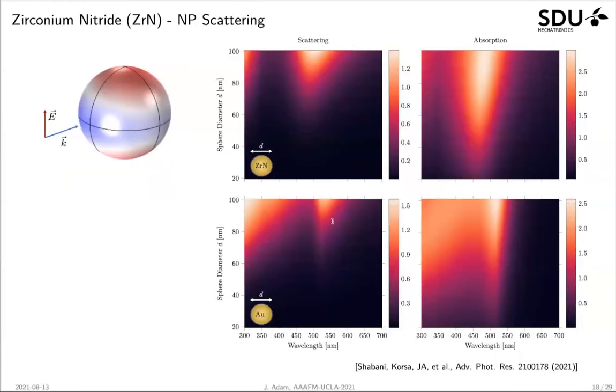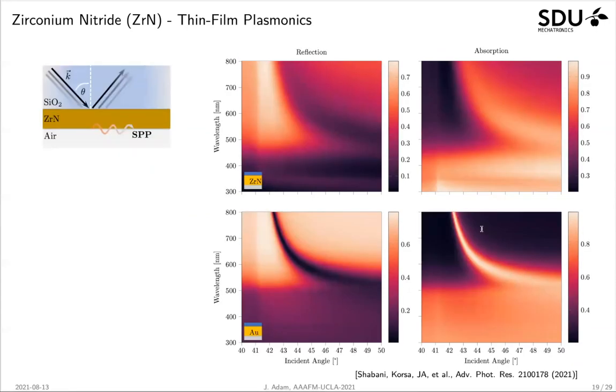Another question is whether this works in classical nanoparticle scattering scenarios, where the gold standard is literally gold. We compared ZrN nanospheres to gold nanospheres and found that in principle the resonances in scattering and absorption from the zirconium nitride sphere are a little bit wider than those from gold, but they show very similar behavior. In a classical Kretschmann configuration, the resonances created by gold are sharper, but zirconium nitride shows the same behavior with shallower resonances. In applications requiring stability, this may be a very valid alternative to classical gold.